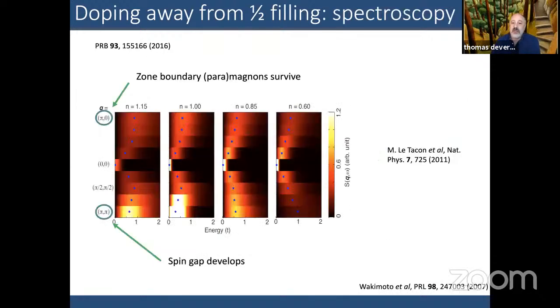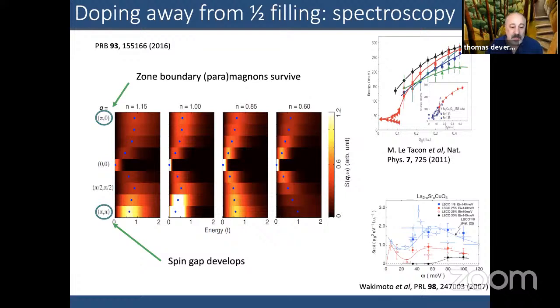Okay. And if you look at calculations for S of Q and omega, the dynamical structure factor, which is plotted here, the quantum Monte Carlo, two things happen. Half filling is N equals one. So if you want to start, let's see if my little mouse works here. I don't know if you can see it, but started here, that's half filling. So you see you have bright intensity at low energies at (pi, pi), corresponding to the antiferromagnet and the peak at pi over two and at (pi, 0), the top of the magnon band. And if you look down here at (pi, pi), if you dope, then the spin gap develops. So the intensity of the peak comes down differently if you dope with holes or dope with electrons. And the energy of the spin gap increases with doping until around 60%. It's on the order of T or so, and the intensity is gone.